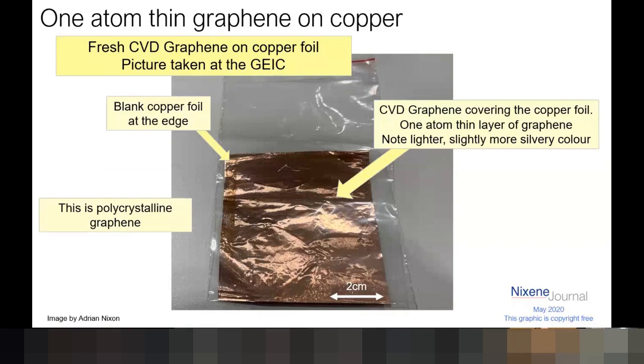And this is what it looks like. What you're looking at here is a piece of copper foil with a 1 atom thin covering of graphene on it. And the amazing thing is, if you look closely, you can actually see that 1 atom thin layer of graphene. Can you see down the left-hand edge? There's that slightly darker strip. That's the blank copper foil. And then on the right-hand side, the larger area, it's got more of a silvery sheen to it. That's the 1 atom thin layer of graphene. You're actually seeing graphene. And graphene absorbs 2.3% of the light that shines on it, which is astonishing for a 1 atom thin layer. We'll come back to that later. So that's what the CVD sheet graphene looks like when it's made on copper foil.